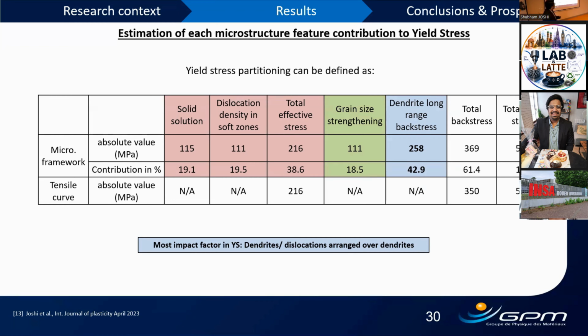It works. And another aspect, if we look at the contribution percentage of all the microstructural features, close to 18 to 19% is for solid solution, dislocation density in soft zones, and grain size. But the most important contribution that we see is from dendrites. So a big conclusion can be laid out here: dendrites are the most influential microstructural feature when it comes to the yield stress of LPBF samples.